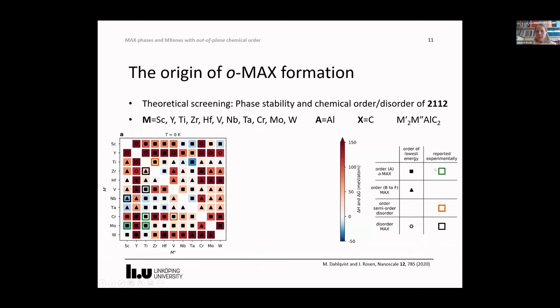If the symbol is surrounded by a square, it has been experimentally reported as OMAX if the square is green, and as a solid solution if the square is black. And experimentally known OMAX phases can be found down here. But as you can see, there are quite a few additional M elements that can form OMAX and that have a blue background. In other words, are predicted stable.